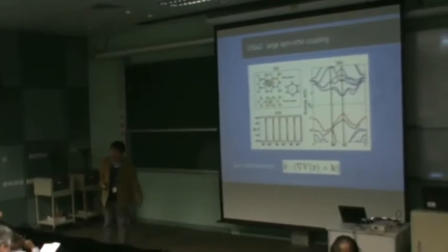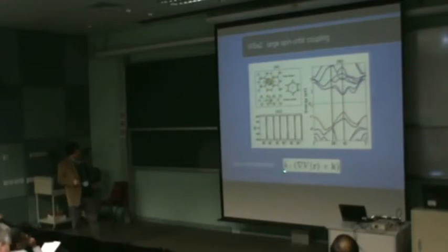And we are interested in transition metal dichalcogenides. Basically, over there is a physics problem: we try to see whether we can use an electric field from outside to tune the spin. Electric control of spin is the holy grail of spintronics. The reason this is possible in this material is that the spin-orbit interaction is very large. Basically, this says my spin is oriented by this term, which is like an effective magnetic field, and this effective magnetic field actually depends on the potential. The potential is given by these atoms, but I can put in an external potential to affect the spin. So the idea is that I can put a gate voltage to gate the spin, which is actually kind of strange when you think about it.